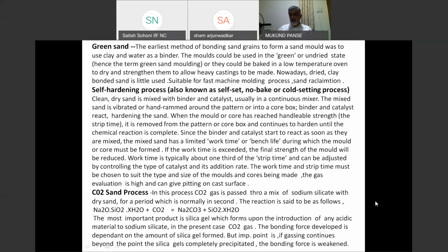The clay develops a layer on the grain. When the grains are rammed and formed together, some strength develops, though the strength is very low. This is a very fast process of molding. Since no gassing is required like the CO2 process, and there is no waiting for the self-hardening process, it is the cheapest process. It is most convenient for machine molding applications like jolting, squeezing, ramming, Harman machines, sand slingers, or turntables, because it is very fast. You can ram the sand and the mold can be stripped. The mold is ready.